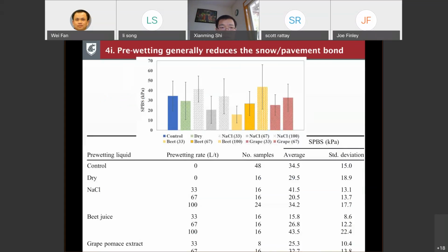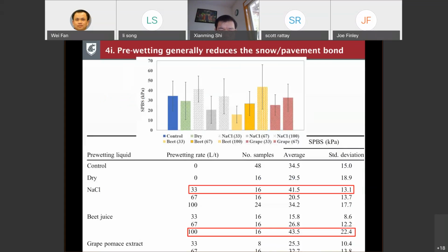But the good news here is pre-wet generally reduces the bond, with two exceptions here. One is when the salt brine was at 8 gallons per ton, and another one is beet juice blend at, I think, 24 gallons per ton. But in most other cases, we are seeing the benefit of reduced bond, especially when the beet juice, again at 8 gallons per ton, seems to be reducing the bond by roughly half.